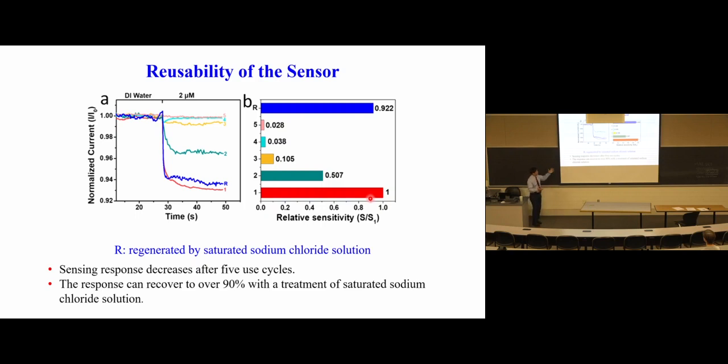So we tested this device a few times. You can see, just after a few tests, the performance significantly degrades so that there's no additional capacity. You will not see any significant response per se. But if you regenerate this sensor in, let's say, a saturated sodium chloride solution, you would be able to restore some of the probes so that you can reuse this sensor device with essentially similar sensitivity. So this shows this type of sensor can be regenerated.